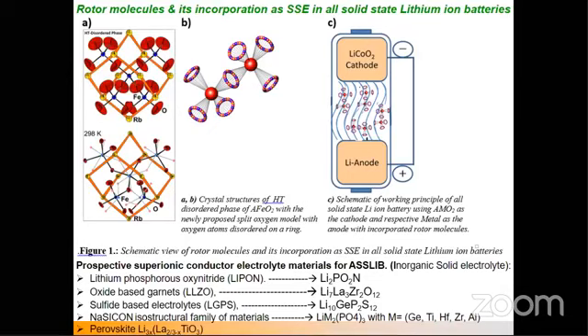In order to remove that risk, we have to replace the liquid electrolyte within the battery with a solid electrolyte. And if you have a solid electrolyte, the major impediment is how to get good lithium-ion conductivity. So rotor molecules have a big role to play in these all-solid-state lithium-ion batteries, where we don't have any liquid. These are the materials in the lower corner which have been extensively used: lithium phosphorus oxynitride (LiPON) based materials, garnets, sulfide-based electrolytes, and so on. NASICON is a very famous material for that application, and also perovskite-based solid-state electrolyte battery materials.